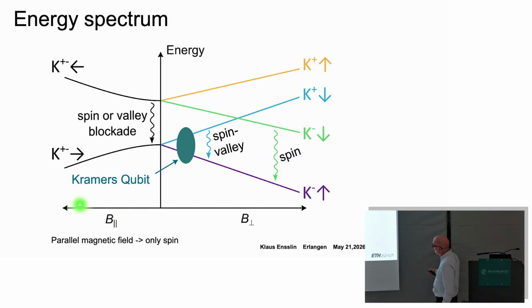It's also interesting what happens if you apply an in-plane magnetic field. Then you don't couple to orbital motion. You don't lift the degeneracy, but you start aligning the spins in the two states in the direction of the magnetic field. Now, I didn't tell you that in my last experiment, a relaxation mechanism plays a role. Let's assume we work here. We go to a small magnetic field. We have the Zeeman split state. We want to go from up here to down here. Then you see you have to flip valley and spin.